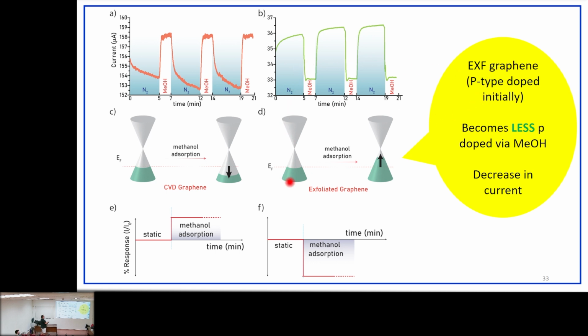And the second thing is, if you have exfoliated graphene, again you have a p-type material. The exfoliated one always behaves like p-type, but this time, because of the direction of charge transfer, you have less p-type doping, then a decrease in the base current. This is why you observe this decrease. Then the scenario is complete, but if I consider the presence of oxygens and other things, it will be more complete, let's say. Theoretically, one can understand those things, and by using DFT it can be calculated.